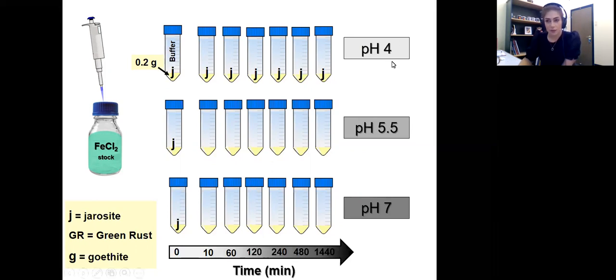So pH 4 resulted in no mineralogical transformation, but it wasn't the case for pH 5.5. Then I added my iron 2 solution to the jarosite suspension at pH 5.5.